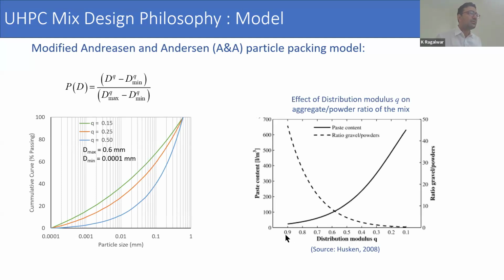that a lower distribution modulus will have higher paste content. And if we have a higher distribution modulus, what it does is that it increases the ratio of gravels to powder. So in general, you would see that the UHPC distribution modulus is in the range of 0.25. That means we have higher paste content. And that also comes from the fact that paste content is defined by anything lower than 50 microns. So cement particles, silica fume, other things that contribute to paste content, and then the lower aggregate forms the gravel or powder ratio.